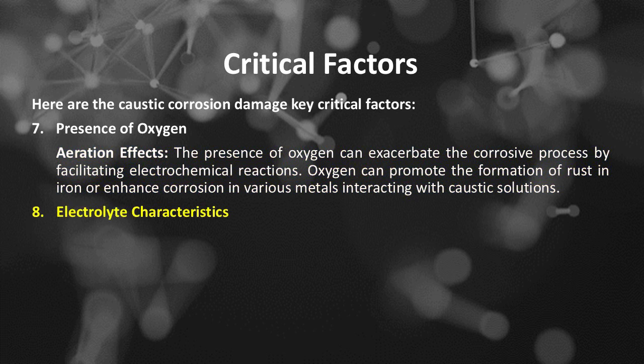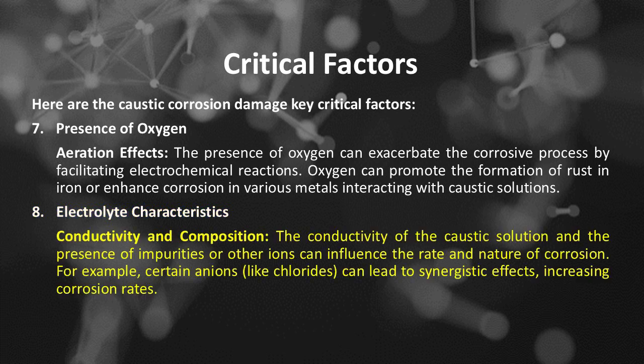Number 8 is electrolyte characteristics. Conductivity and composition. The conductivity of the caustic solution and the presence of impurities or other ions can influence the rate and nature of corrosion. For example, certain anions, like chlorides, can lead to synergistic effects, increasing corrosion rates.